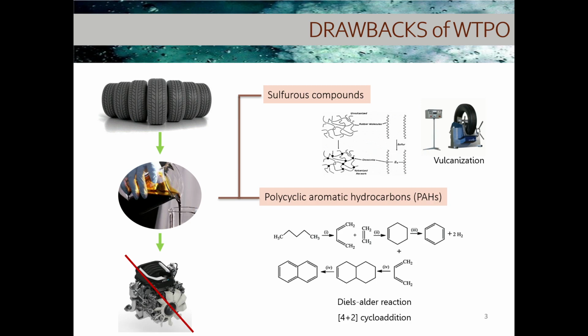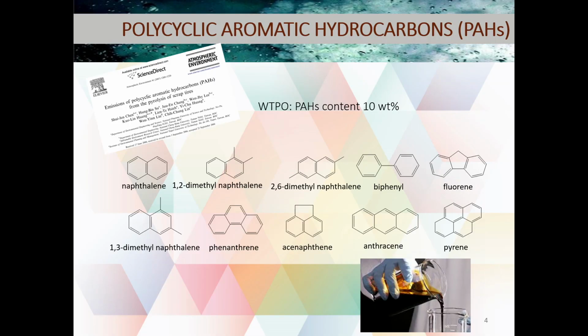Actually, we cannot apply waste-tire pyrolysis oil directly in a combustion engine because it has some toxic compounds, such as sulfurous compounds derived from the vulcanizing agent, and polycyclic aromatic hydrocarbons derived from the Diels-Alder reaction during the pyrolysis process. For the sulfurous compounds, we have the hydrodesulfurization process to decrease the amount of sulfur in the WTPO. But for polycyclic aromatic hydrocarbons, or PAH, there has not been any report yet on decreasing their amount in the WTPO. So in this research, we focus on the PAH inside the WTPO.